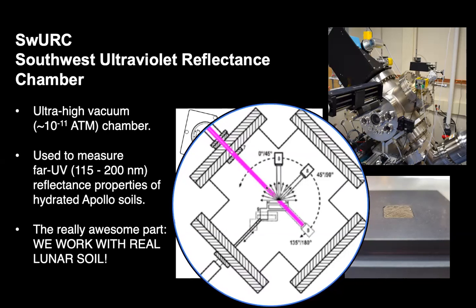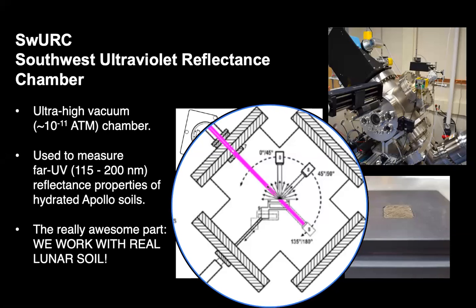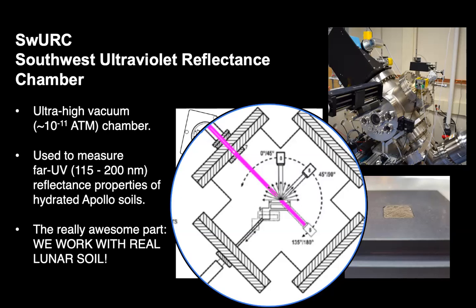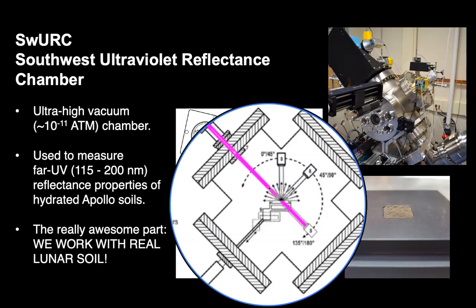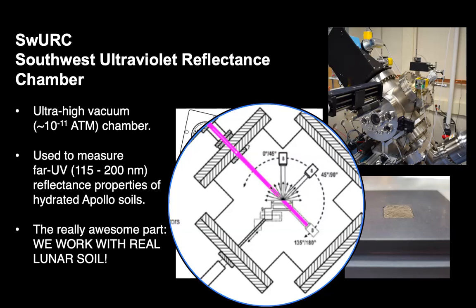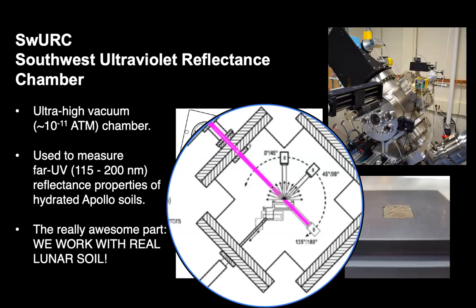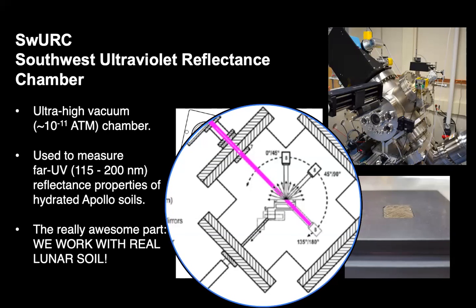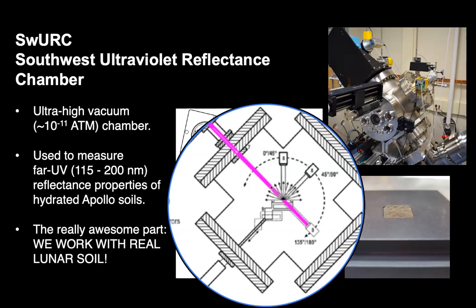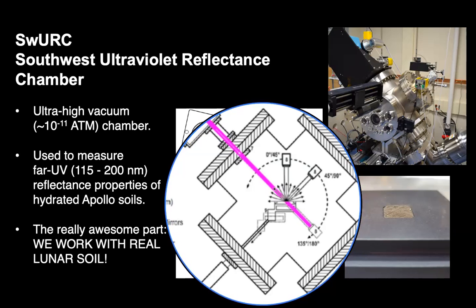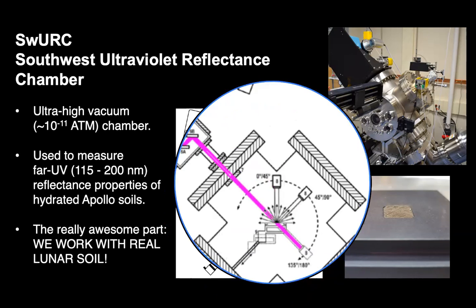That's at exactly 45 degrees, and that can move the sample into and out of the way of the far ultraviolet light beam. The armature that you see there, the smaller rectangle on the longer rectangle that goes around that dotted line circle, that's the detector. That's a channeltron detector that picks up the reflected UV light signal. It can go not quite all the way around the sample, but pretty close to. Not that that really matters that much. What matters here is the fact that it can be brought right into the path of the light and then brought out of it, and with the sample moved into position, it can measure those reflectances.